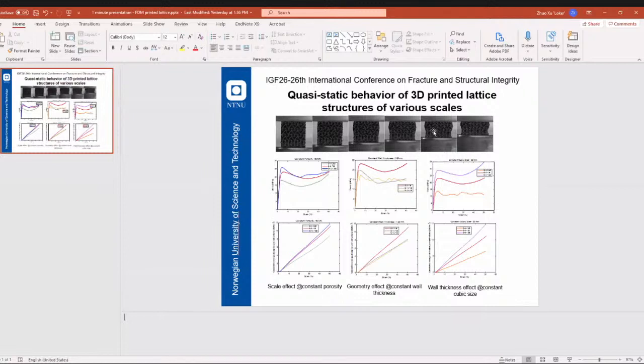For some lattice printing, especially for the very thin walls, if you do the slicing in the software, you will see some walls will only have one line. So it doesn't really matter if we have plus minus 45 or plus minus 90. It will be the same for those lattices. Maybe for the thicker wall thickness, that will vary. Okay.